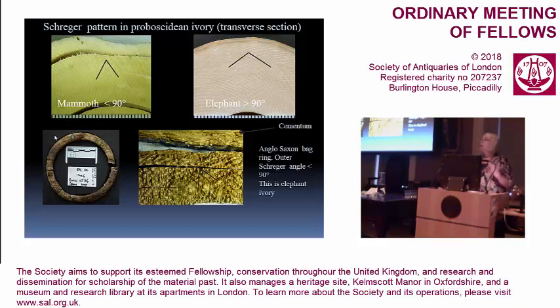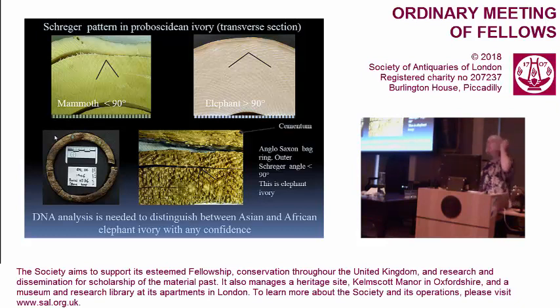What the Schreger pattern cannot do is separate Asian elephant from African elephant — that can't be done structurally. So we can't take identification down to absolute species. There's been a long debate about Anglo-Saxon bag ring concerning the source of the ivory — I can't say if it's African or Asian, but I can confirm it is elephant and not mammoth from the Schreger angle. The only way to separate those species, as I've said, is using DNA, which is of course destructive, and mostly we can't really afford to do that.